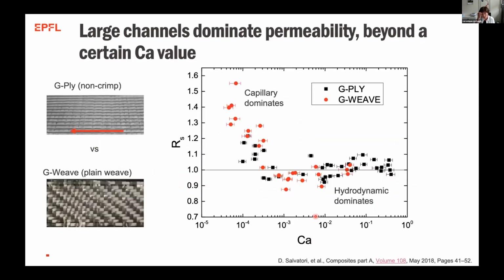And then we found, interestingly, that if you do a wide range of capillary numbers, the RS ratio in this case was very high at low capillary numbers. So the capillary effect dominates. That's what we expected. And if we go very, very slowly, everything is just sucked up in the toes.